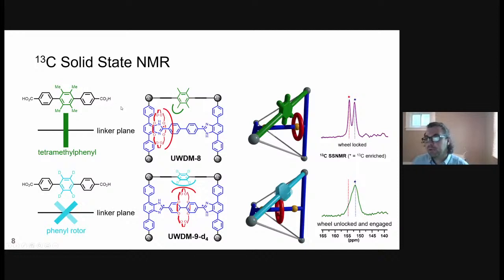So if we first start off with the carbon-13 solid state NMR, which we use to understand the position of this crown ether macrocycle. For UWDM8, when we have this tetramethyl spacer, which is perpendicular to the linker plane, when we conducted the variable temperature solid state NMR measurements, we saw across all temperatures, this is just a room temperature spectrum here, 2 peaks corresponding to this carbon-13 enriched position. The upfield peak corresponds to the unbound recognition site, and this one here in red, the downfield peak, corresponds to this recognition site binding the crown ether macrocycle. And as we see simply 2 peaks across all temperatures, that indicates that any motion is slower than the NMR timescale, and this effectively means that we have shut off any translational motion and we have the ring locked at one end or the other. And this makes sense when we consider the steric bulk imposed by this tetramethyl phenyl spacer.